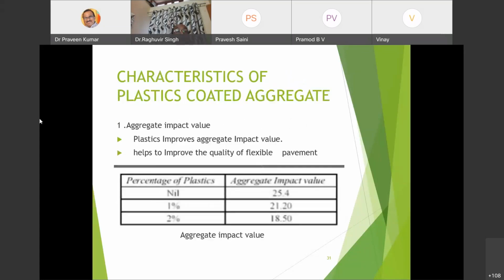Sir, characteristics of plastic coated aggregate: aggregate impact value. Plastic improves the aggregate impact value and helps to improve the quality of flexible pavement. The normal aggregate impact value was checked, and it was 25.4%. Then, adding plastic waste with bitumen at 1%, the aggregate impact value reduced from 25.4 to 21.20. So the impact value reduced, which means the aggregate is more sound.